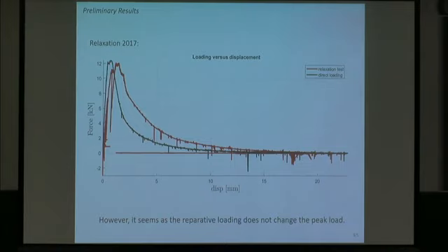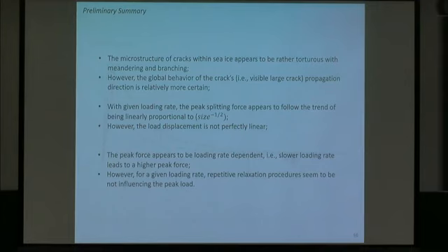I think my time is almost up, and I would like to make some summary. Note here that it's not a conclusion, because after processing these results, it seems that I'm just opening a can of worms. It's just more questions coming to me, and it seems like I can really go in opposite directions. First, we can see that at the microscopic level, the crack really meanders and branches. But globally, it seems that the crack has a relatively determined direction to go. And I have to thank John. John worked out this 2-to-1 ratio, which makes the crack direction relatively more controlled,